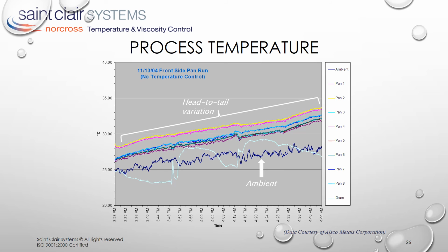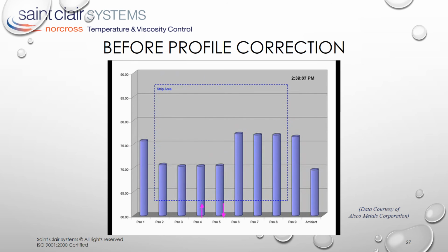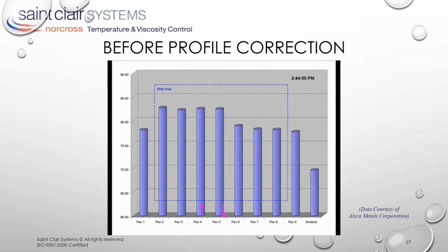The problem is that this friction also creates a 3 degrees C variation across the width of the rolls, which we see as the vertical displacement of the traces. It's all because of the flow dynamic in the coating in the system, but manifests itself as edge-to-edge variation. It's actually easier to see and analyze if you view it time-lapsed like this. This is an excellent example of how these swirls and eddy currents affect the performance of the coater. We call this an uncorrected profile. Of particular interest is the stark difference between pan 5 and pan 6 over just a short distance. It is nearly impossible to compensate for this stark change using just the adjustments at each end of the nip.